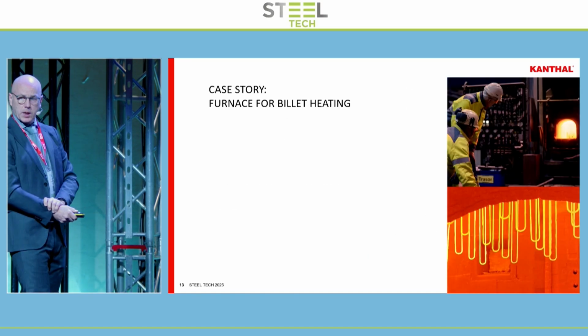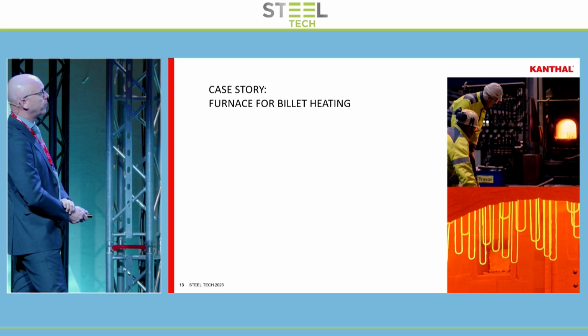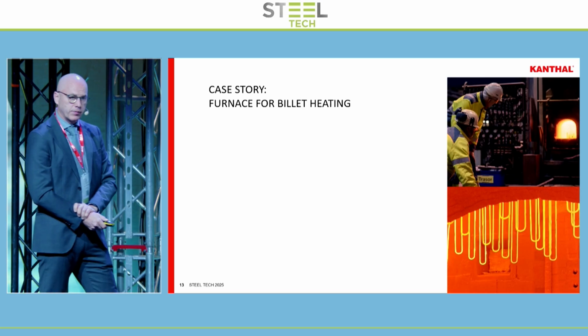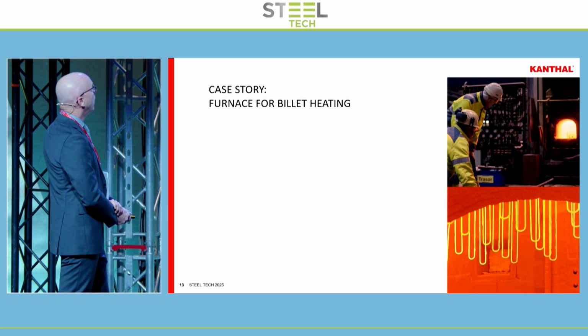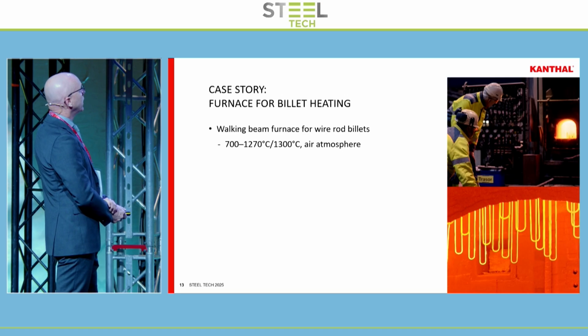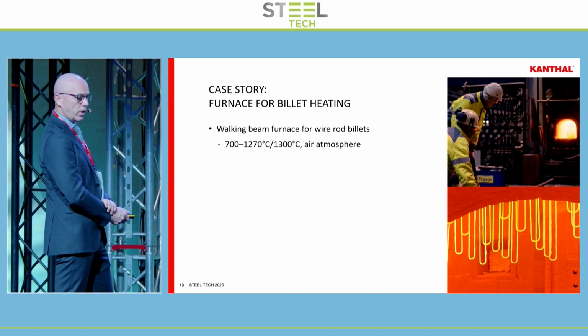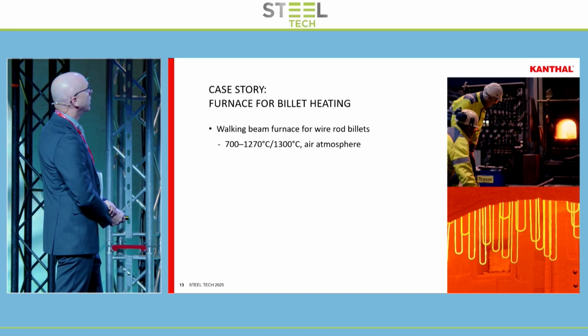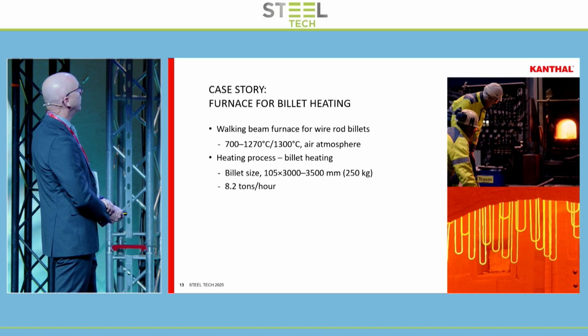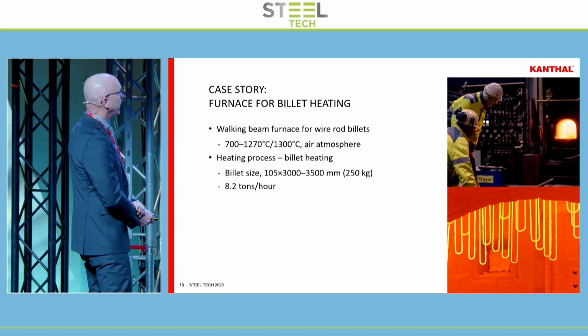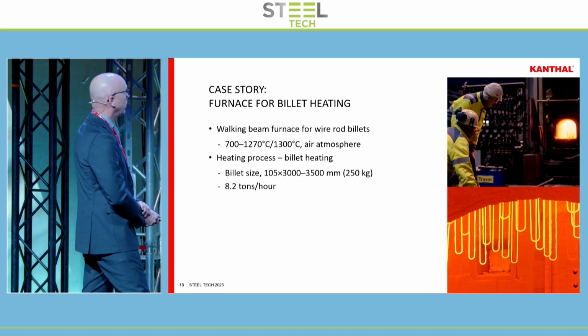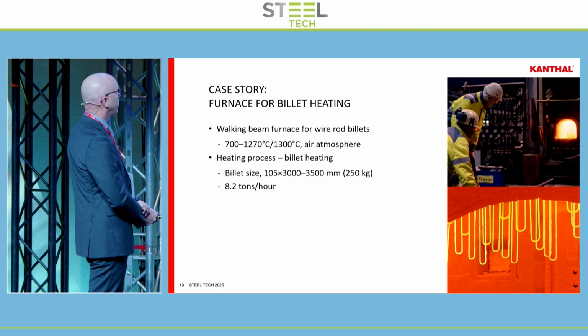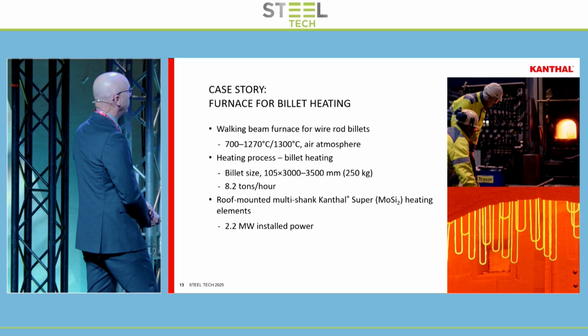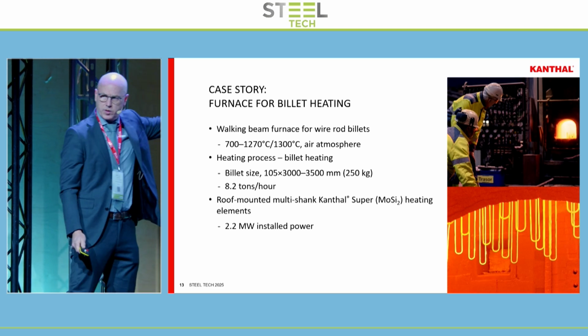Just a couple of case stories there. We have a furnace for billet heating at Kanthal, at our facility there. We have a walking beam furnace there, up to about 1270 degrees centigrade with air. The billets are not large, and it's not a large furnace, but say 8 tons per hour. It's about 2.2 megawatts installed power.